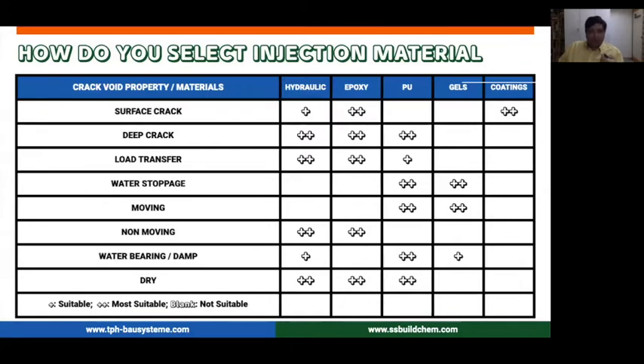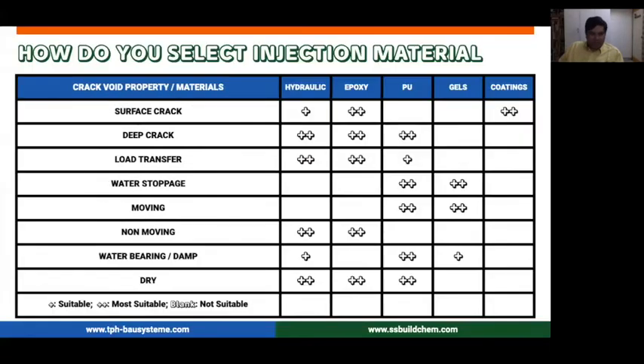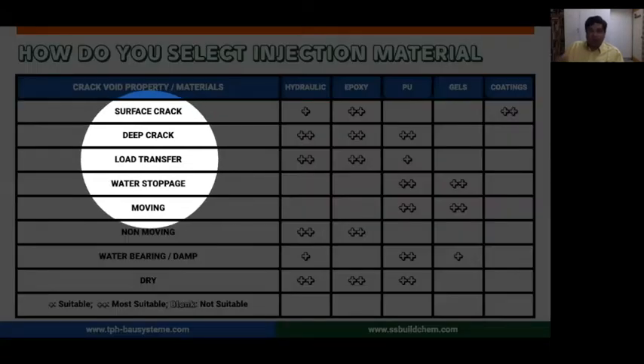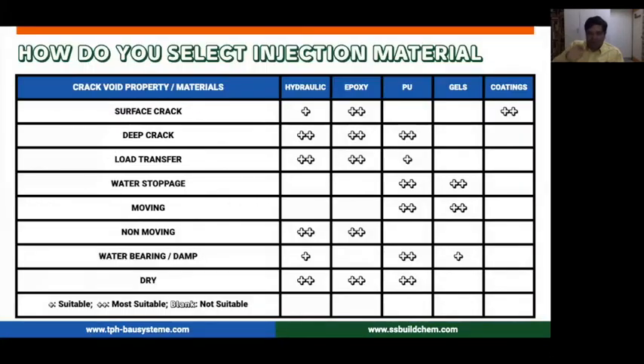So now, again, the injection material selection is based on a variety of factors, like whether it's a surface crack or a deep crack. But when we talk about repair and rehabilitation, what we're looking to do is transfer loads. That means you have your crack face and you want to transfer the load from one face of the crack to the other side. So in that case, the best two options that you can follow would be using a hydraulic or cement injection system, or an epoxy injection system.